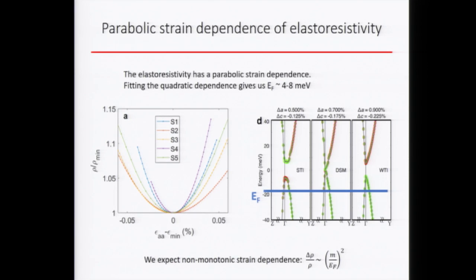And this is indeed what we see. As a function of strain, the resistance changes by about 10 or 20% with less than 0.1% change of strain. That's a huge change of resistance with such a small amount of strain. But most strikingly, there is this non-monotonic dependence. You just don't expect that in an ordinary semiconductor. In an ordinary semiconductor, you sometimes get like a 100-fold enhancement of your change of resistance over strain, but you always expect a linear response. So this nonlinear response is really telling you something singular is happening in the electronic structure. And the most natural explanation is that you're switching the mass from positive.